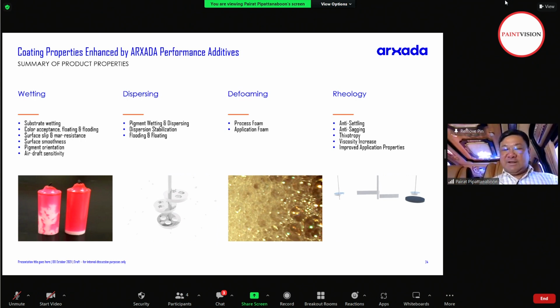Defoaming additives help you control process foam and application foam, plus maintain or improve your gloss. Lastly, rheology modifiers provide properties to control application viscosity, low shear and high shear at application, and low shear for storage stability or transportation. They provide anti-settling, particularly for matting agents like fumed silica in your matte coating products, and control anti-sagging for products applied at wall level. They provide thixotropy for your paint, and improve the stability of pigments, especially metallic pigments and silica pigments, in your formulation for long-term stability.